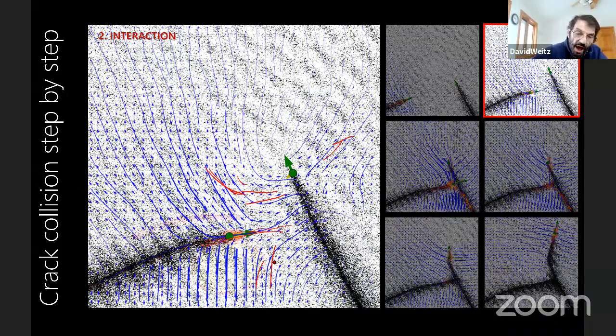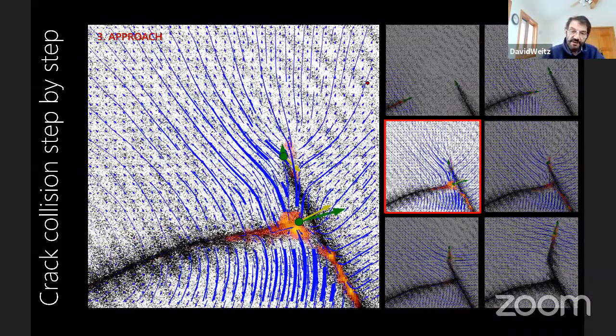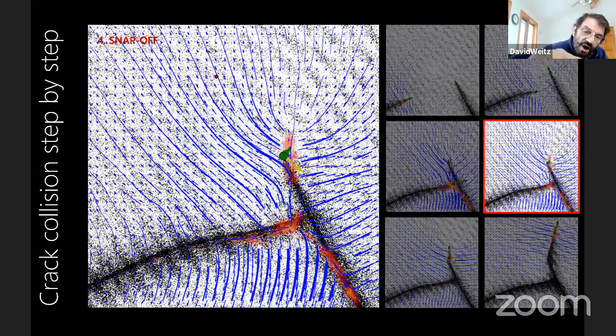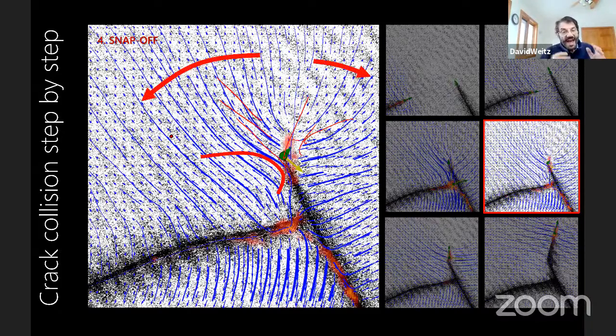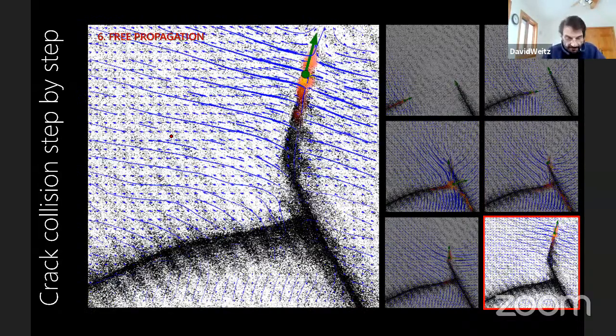And here they come together, and look, you can see the whole strain field. You can see the interactions of the strain field like this, and then this is where they collide. And then because the strain is like this, the strain is driving quite far away. It's driving this crack to change its direction. Now you can see, because there's a combination of the strain fields, it causes this crack, the second crack, to recoil and to move off in a new direction. And you can understand that, because you can measure the strain field quite far away.